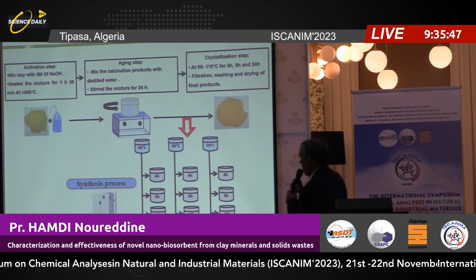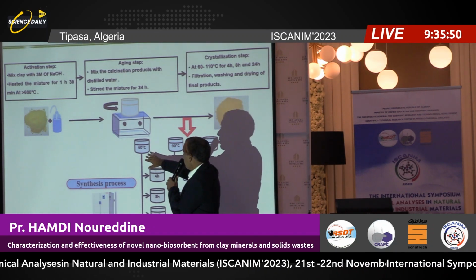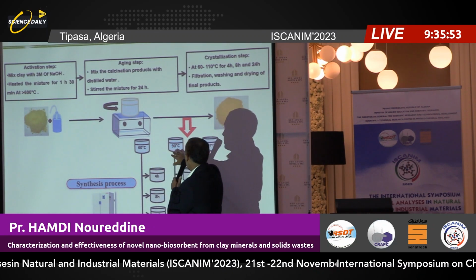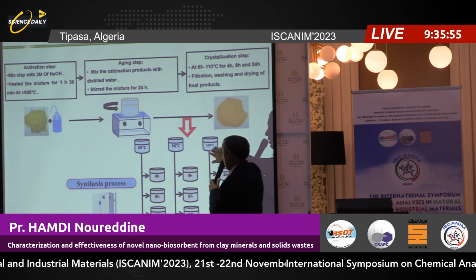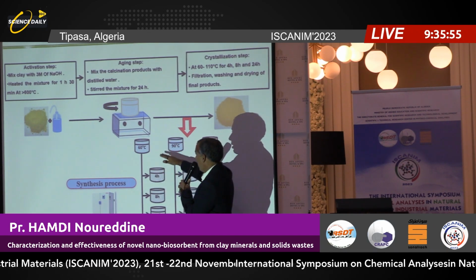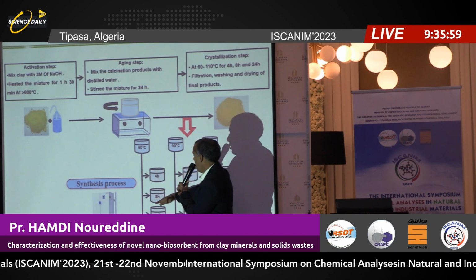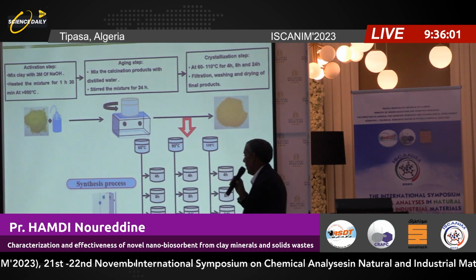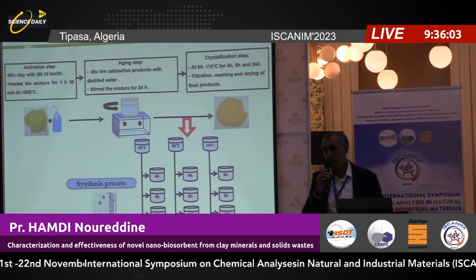Here we used 3 temperatures for the synthesis of zeolite: 60 degrees C, 90 degrees C, and 110 degrees C. And in any case, we used 3 times: 4, 8, and 24 hours.